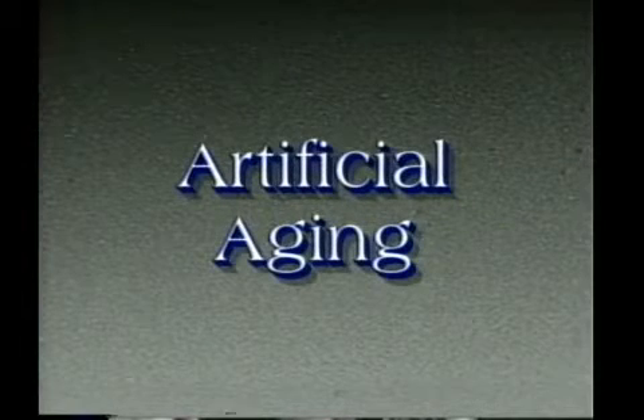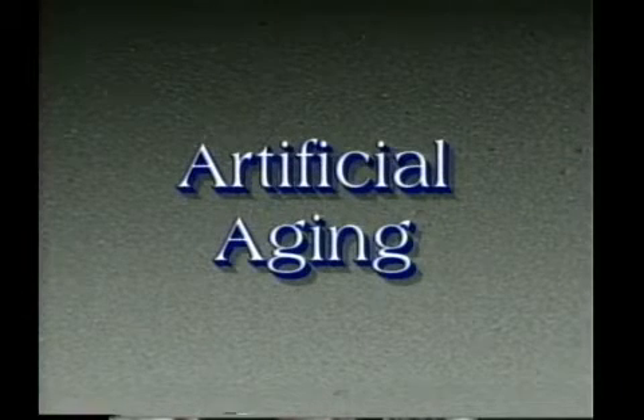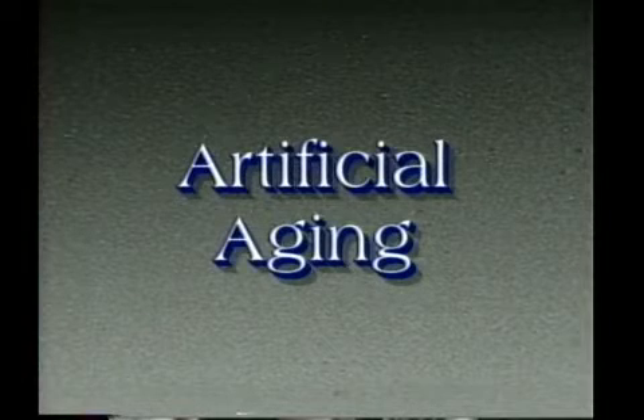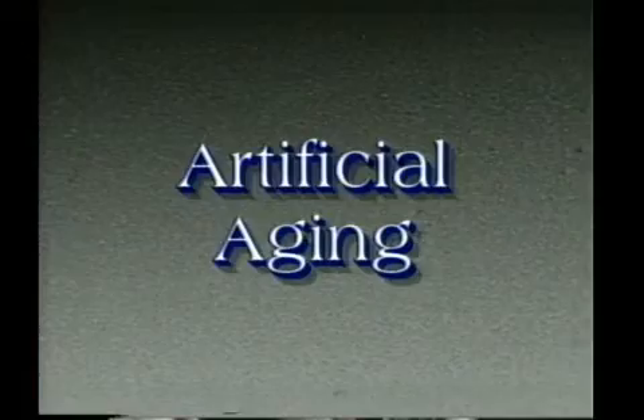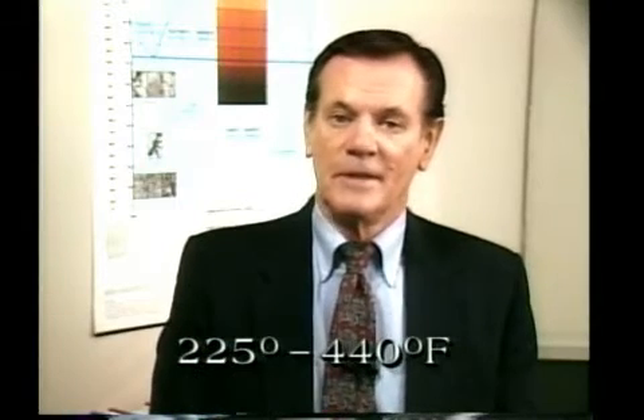For most high-strength alloys, the highest strength, maximum stability, and optimum corrosion resistance are achieved by artificial aging. In the artificial aging procedure, the material is heated for the required length of time at some elevated temperature, usually from 225 to 440 degrees. The time will vary depending upon the temperature selected and the properties desired. The strength increase achieved by artificial aging of most high-strength aluminum alloys is significant and can be as great as 4 times greater than the as-quenched strength.